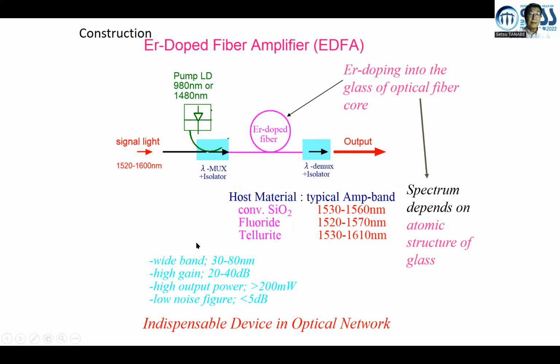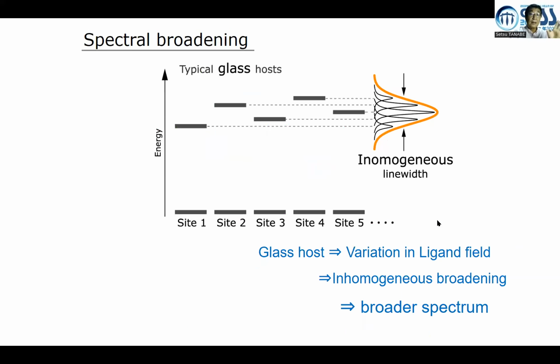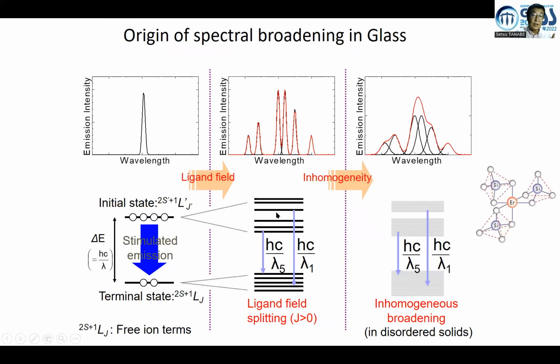Depending on the glass host material, the amplifier band is different. Silica has a rather narrow amplification band, fluoride is broader, and tellurite is much broader toward longer wavelengths. So tellurite glass might be a good host material for broadband wavelength division multiplexing, and the spectrum depends on the local atomic structure around erbium ions in glass. Intrinsically, amorphous material often gives inhomogeneous broadening, even though the singlet has no splitting structure. As well as that, because of the Stark splitting, the spectrum of erbium